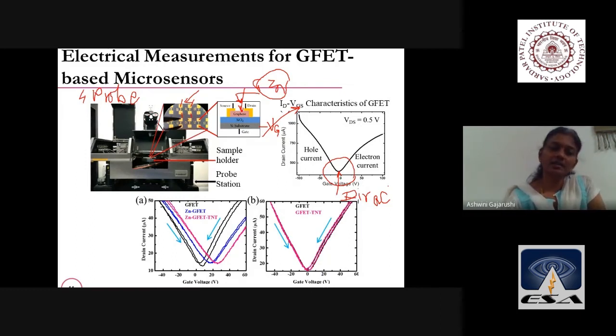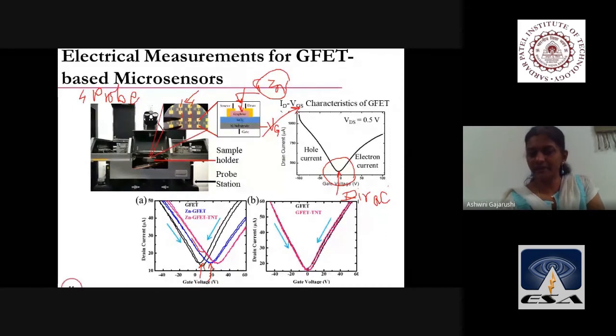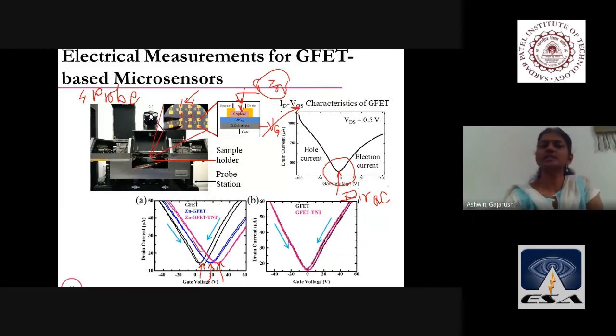Now what happened? This ID-VG curve, black color, is for a simple graphene transistor. Then the blue color is a curve for the zinc modified graphene transistor, and pink color is after the TNT. So what happens when we modify the graphene transistor with this zinc modified material? At that time this Dirac point, can you see this Dirac point? This Dirac point has shifted to some higher value. Say it was around +5 volt before. Now it is around +18 volt. And when TNT flows, it further shifts to around +28 volt. So this shift in Dirac point is a sensing parameter for this particular system.